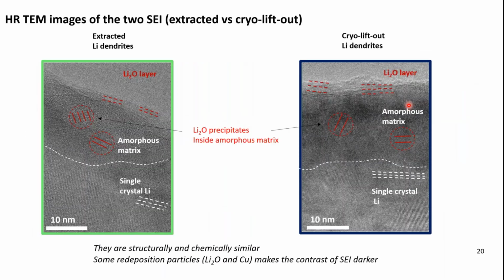We can also go for high resolution imaging. The extracted lithium dendrites seem to have layered lithium oxide structures at the edge, with some precipitates inside the amorphous matrix. We have similar structures in the other sample, a lithium oxide layer at the edge and lithium precipitates inside the matrix. The reason why it looks darker is partially because we have redeposition of lithium oxide and copper, which usually occurs in porous samples, and our dendrite samples are quite porous, so some of the splashed redeposition precipitates at the edge of the lithium dendrites, and there was SEI in this region.